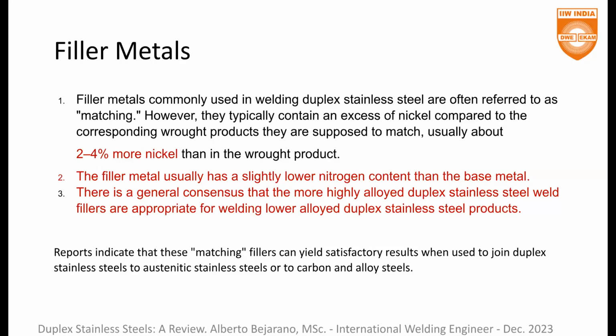Someone is talking, I think it was some noise. You can go ahead. Okay, thank you. So if we use filler metal, we add from 2% to 4% of nickel in the filler metal, because nickel promotes the austenite. Remember the key here is austenite. We love ferrite, but we do really need austenite. Okay, very well.